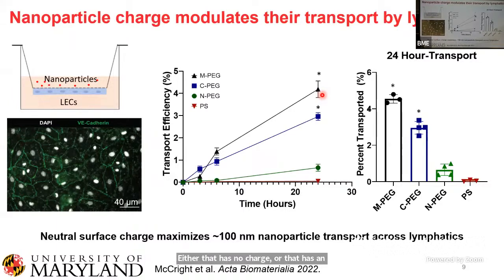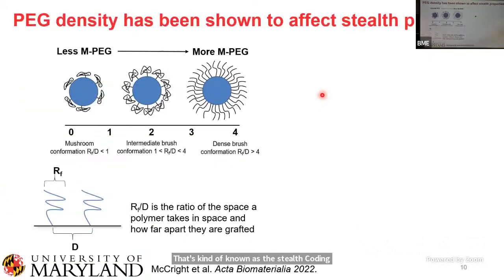And so knowing this, and with some of the work that I had done on trying to understand how to get nanoparticles past the mucus barrier, we started also asking, okay, charge is one thing, and PEG is one of those things that has been used a lot already in the literature, but how much PEG do you need? Do you need a lot of PEG? Is a little bit of PEG enough? So we started making particles with different densities of PEG on the surface.